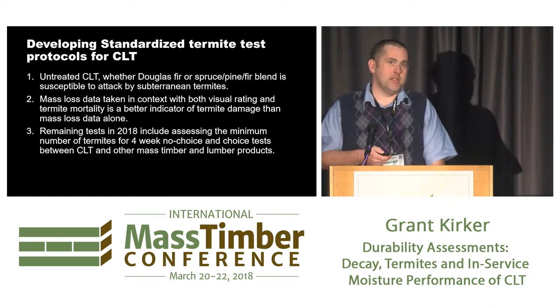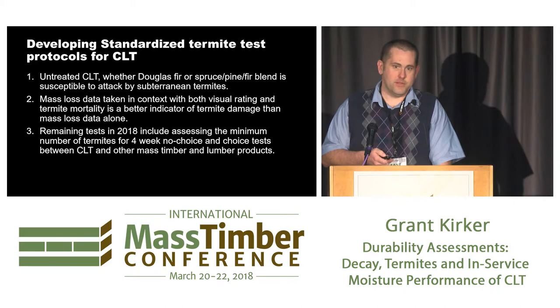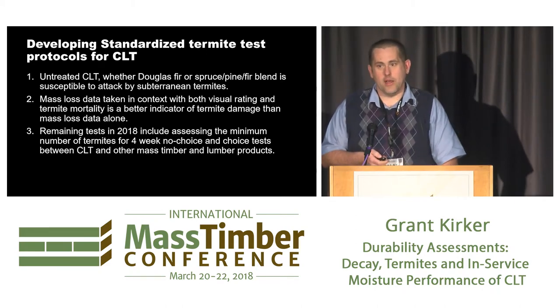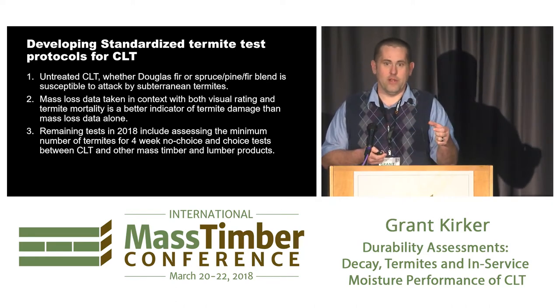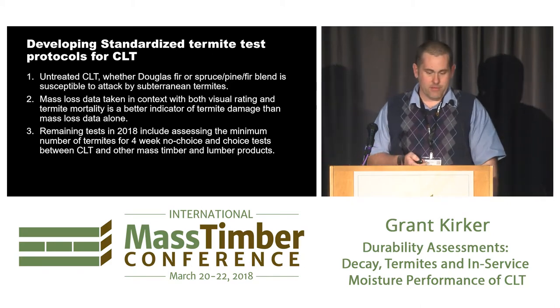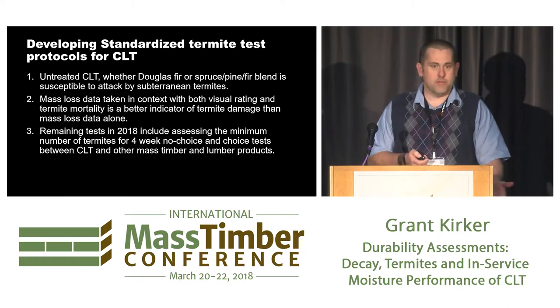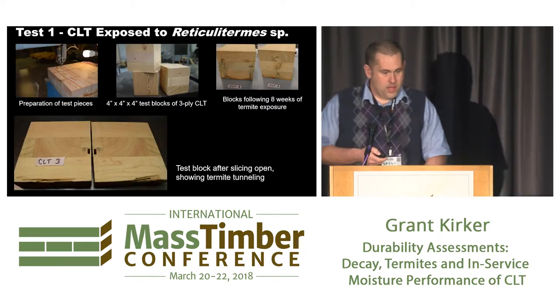And it specifies 300 termites with like a 5-to-1 soldier to worker ratio. I might have got that backwards. And that's specifically for a wafer that we use. So now we're like 10 times bigger, so we're having to adjust the number of termites that we introduce in the test also to get meaningful results. So still some modification going on there.